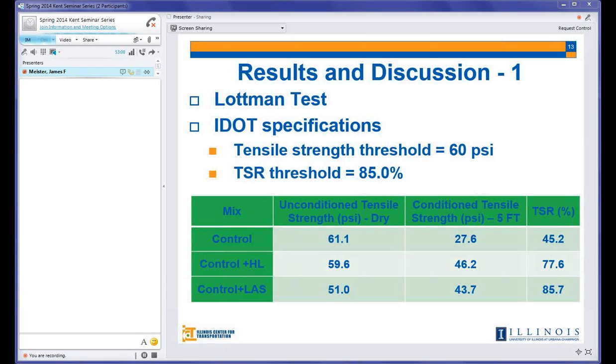The best performance, of course, was for liquid antistrip. In other words, strength-wise, this is the weakest one, but moisture resistance-wise, it is the best. It was able to sustain most of its load after 5 freezing-thawing cycles, and 5 freezing-thawing cycles is a lot for asphalt mixes, especially this weak mix.